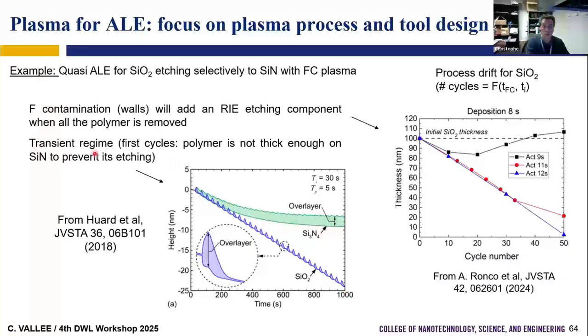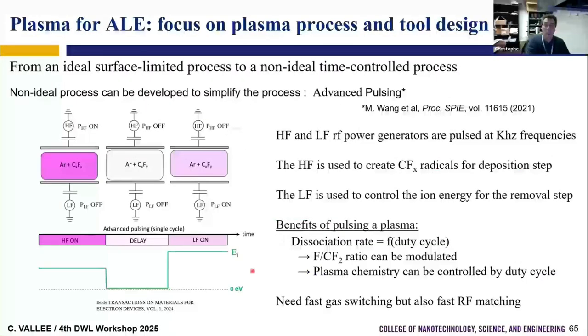So we may have some transient regime where we may start, at the very beginning, to etch also silicon nitride versus silicon oxide. Another design, and to simplify, the most we can simplify is the advanced pulsing from TEL again. So I keep the example from TEL, where we still have the atomic layer etching with fluorocarbon, but now fluorocarbon is no more pulsed. We only pulse the plasma, and we play with the plasma with the on-off of the source. So the source is on, the source is off.